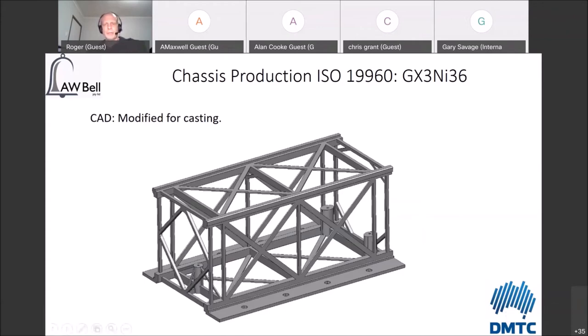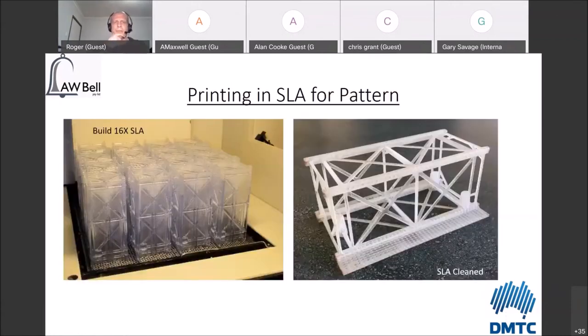So we went down the path. We started with the CAD file, and we went down the path of building these on our SLA printer. Now, an SLA printer is a 3D printing method where you're building up the part layer by layer, and you come out with a plastic part at the end, which you then clean up and prepare. So basically what you see on the left-hand side is 16 of the chassis bodies, the satellite chassis body, coming out of the printer. One of the things that we're able to demonstrate with this is that, without having tooling, we can print off around about 16 of these a day. And that gives you some idea about what the potential size of batches is going to be.